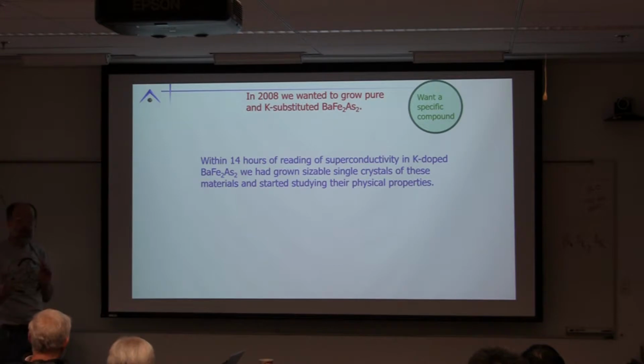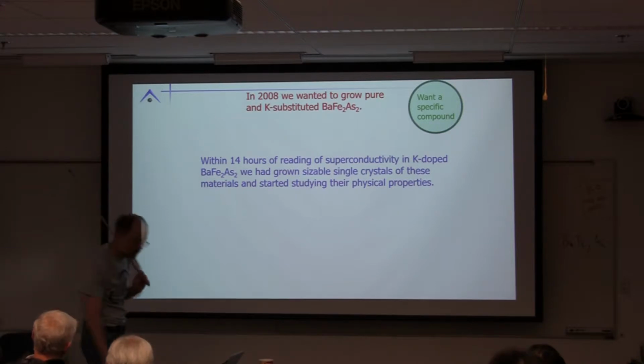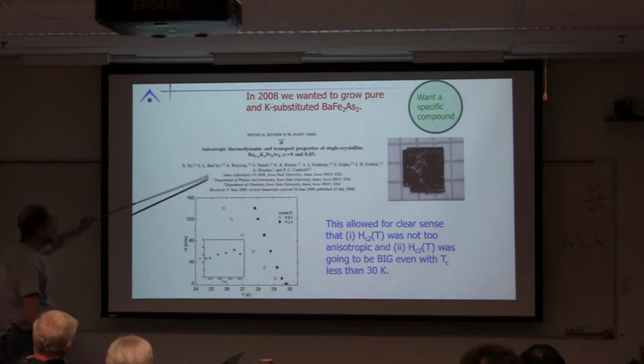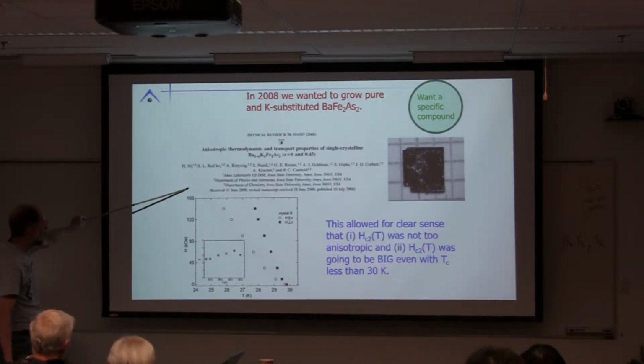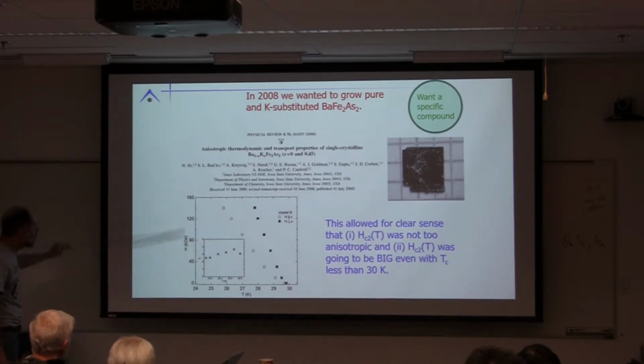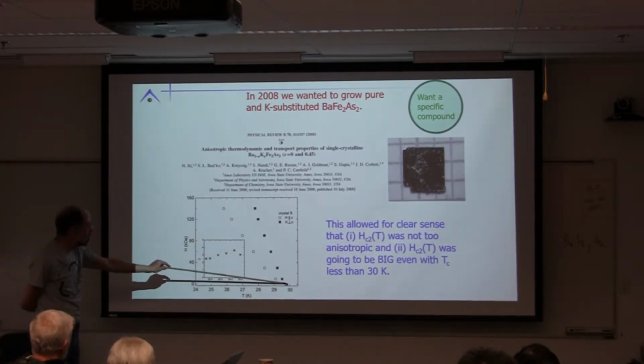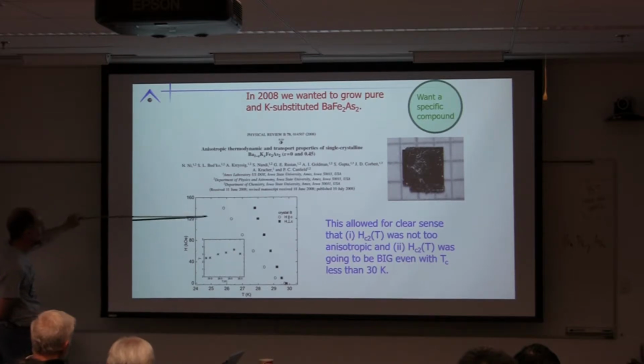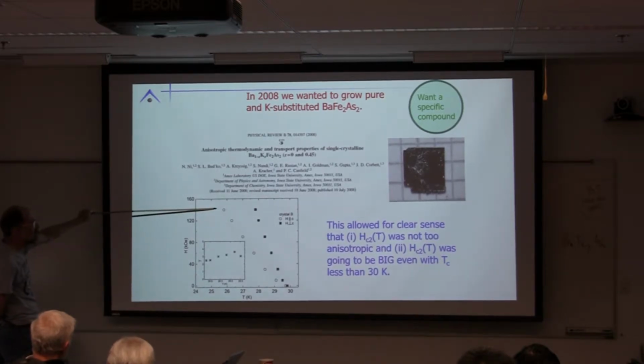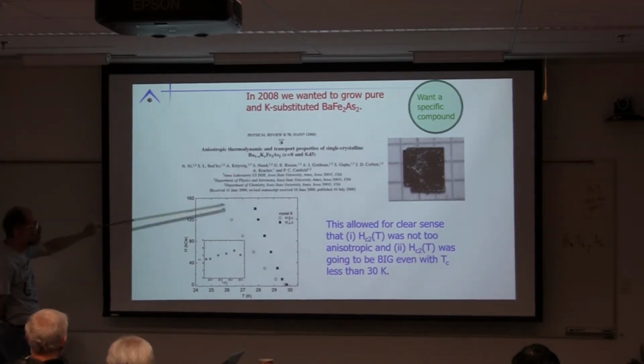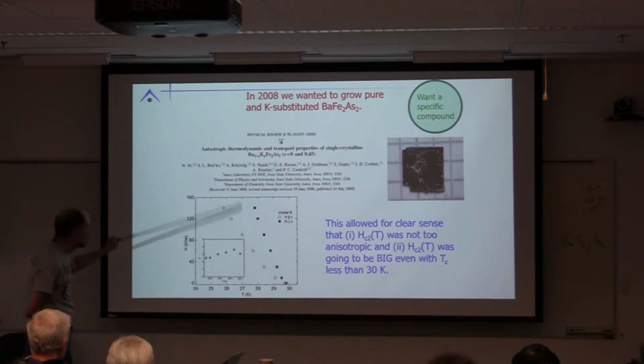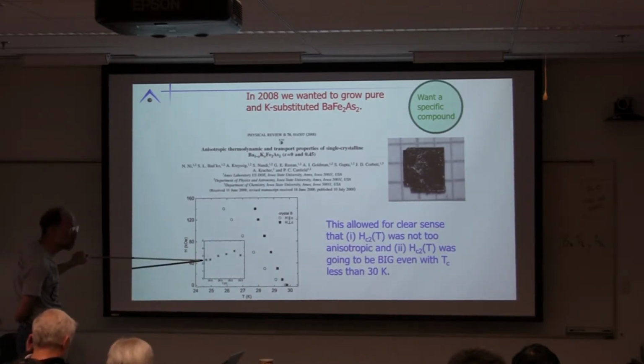Materials work is a lot like cooking. And I mean that in the highest praise, in the sense that it is based on experience, intuition, and creativity. So, with single crystals, we can start measuring anisotropic properties. So here's the Hc2. This has a TC a little below 30, and by 14 Tesla, we're barely suppressing TC. So it was immediately clear that we were going to have a huge Hc2, and also if we look at this, the anisotropy is not very large.